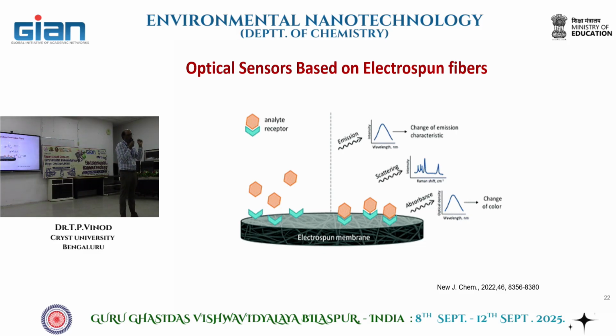So if you can incorporate these metal nanoparticles into electrospun membranes, or you make electrospun membranes and coat them with metal, then you have a nanostructured surface which is very much applicable for the SERS activity.